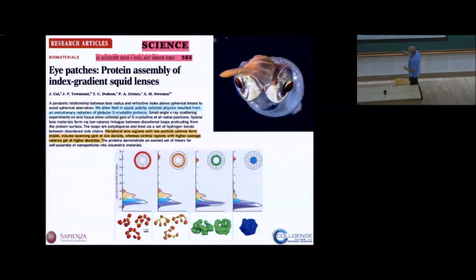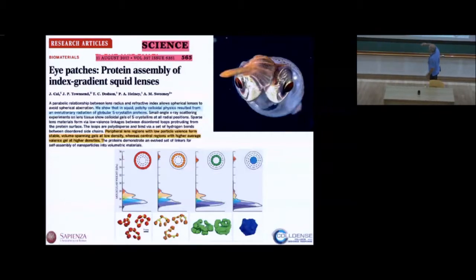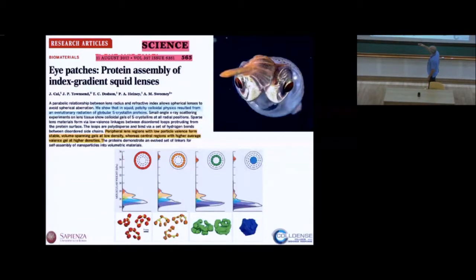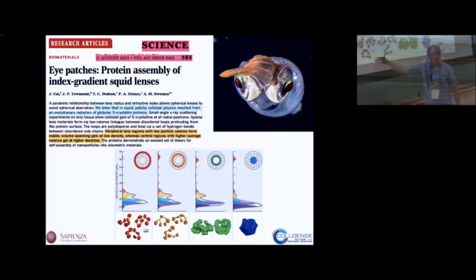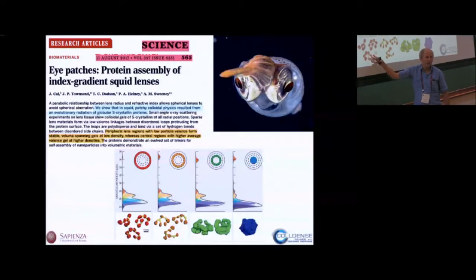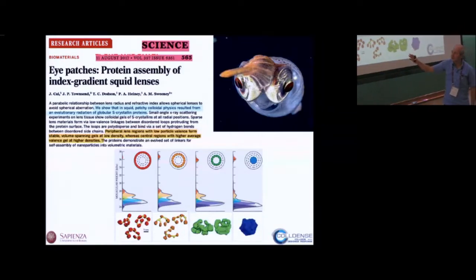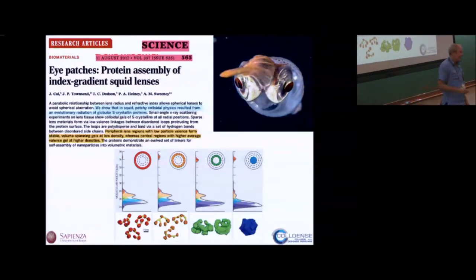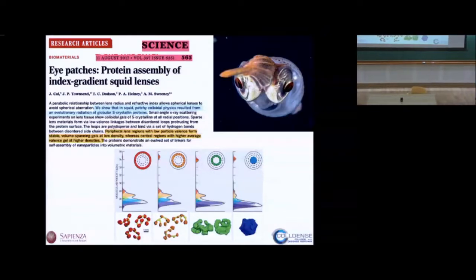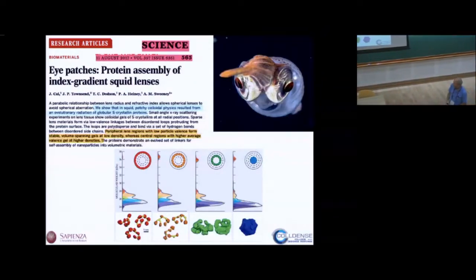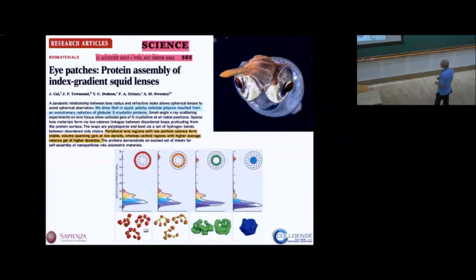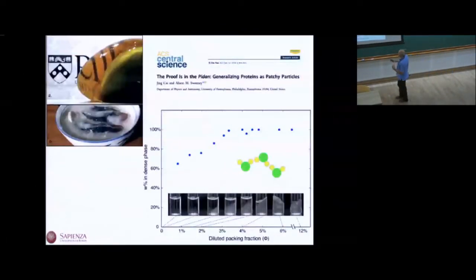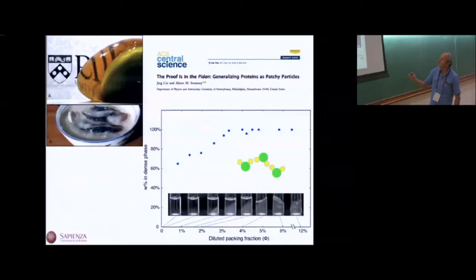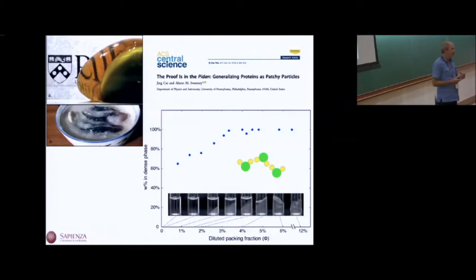And so this group in Philadelphia, Alison Sweeney, has been able to do all the biological work, look at the molecules which are expressed, look at the scattering of those molecules, and realize that particles which are at the outside of this lens form objects with valence 2, and then particles which are inside form much more compact structures. So you go from 2 to higher valence. So nature has selected the proteins in such a way to use this colloidal physics of the low-density patchy particles. And more recently, the same group has reported also another biological system.